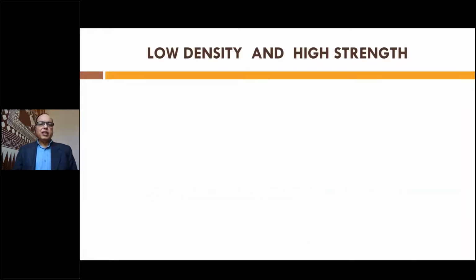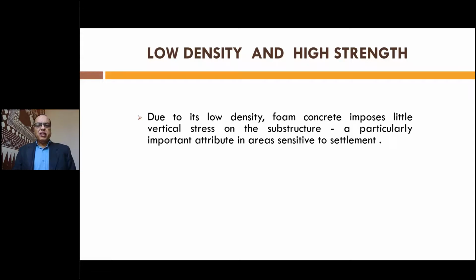Now, the advantage of this foam concrete is that the density would be quite low and the strength would be fairly good. I don't say we can make M60 or M80 concrete with foam, but for most of our structures, it is not just strength that matters, it is the ease with which you can use that concrete. It has a very low density compared to the normal concrete density of 2,500 kg per cubic meter. This can have a density of say 1,600 or 1,200 or even 800, or it can go as low as 600. But if you use 600 or 700, the strength is likely to be less, maybe about 5 MPa or 8 MPa.